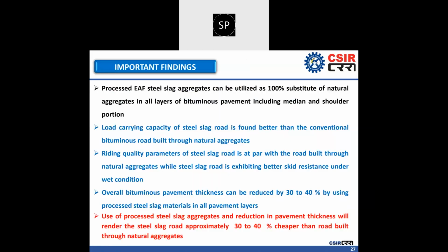Now, what are the important findings? Processed EAF steel slag aggregate, which I have shown you in the previous slide, can be utilized as a 100% substitute of natural aggregate in all layers of bituminous pavement, including median and shoulder portion. So this particular study has proven that the entire road structure can be built through slag aggregate without using natural aggregate inside it. Load carrying capacity of steel slag road is found better than the conventional bituminous road built through natural aggregate.